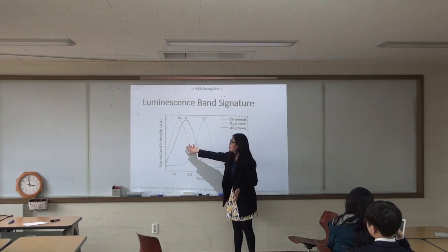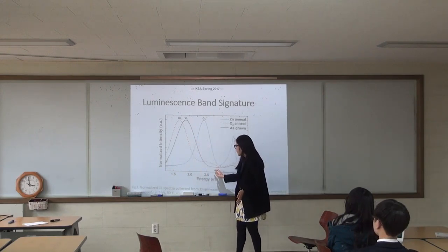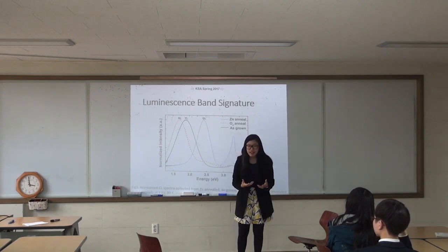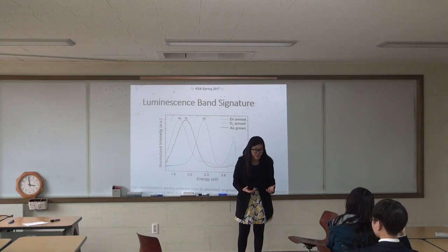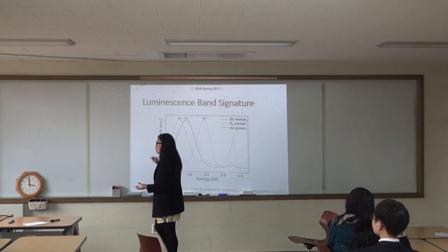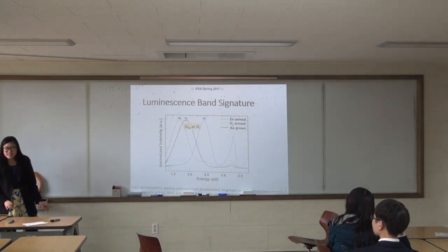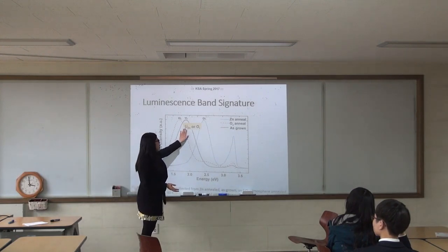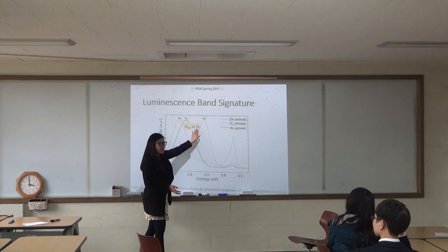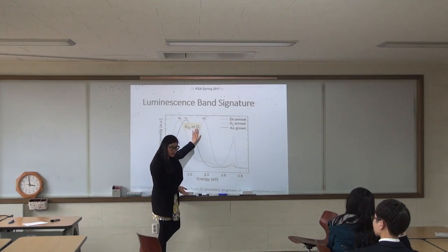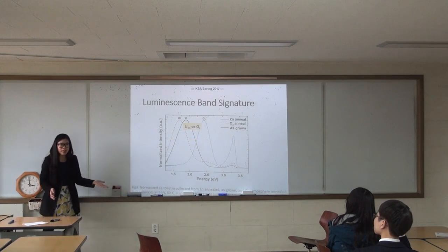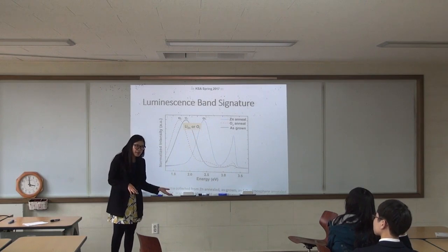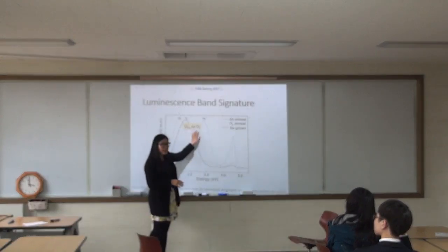But here, you can see that the wavelength or the energy is shifted because it has produced some defect in the structure. For the as-grown sample, it produced yellow luminescence, which most of the published papers agree comes from lithium impurity or oxygen interstitial. But in our sample, the starting material has no lithium, right? Maybe it can be an impurity, but I guess it could be oxygen interstitial.